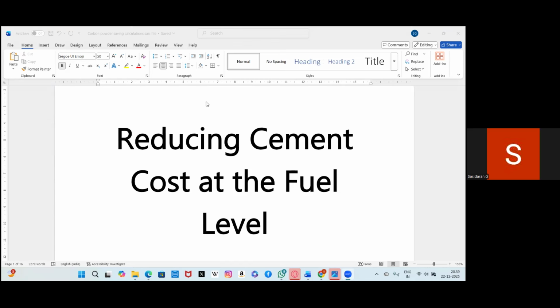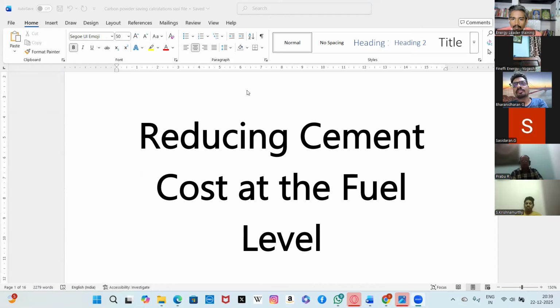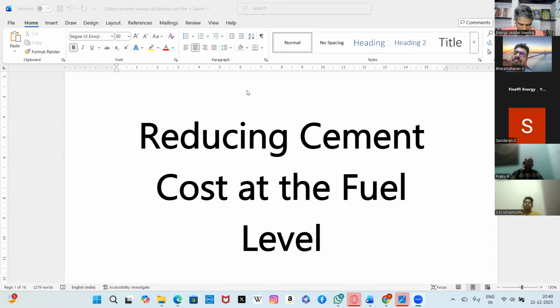portion in coal, sir, since cement operation is one of the biggest and toughest operations. If you see the calcination, the raw material is first taken from the earth. If it is taken as huge lumps, like bigger stones with a size of more than 1 meter, it cannot be directly made to undergo heat treatment. It should be processed to a size of 90 micron, with at most 2% or 3% residue, because it will be like talcum powder. So we process it by reducing the size of the product.